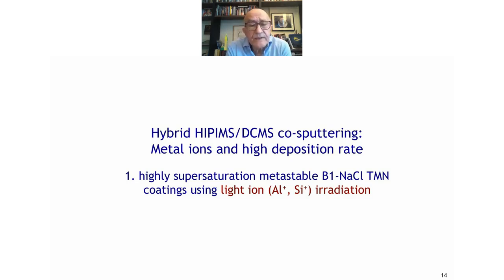Now, for the rest of the talk, I'll use a hybrid HiPIMS and DC magnetron sputtering configuration, where we use metal ions from the HiPIMS discharge and the high deposition rate from the DC magnetron sputtering. And the first half of it will be dealing with producing highly supersaturated metastable cubic transition metal nitrides using light ions, aluminum and silicon. Next slide.